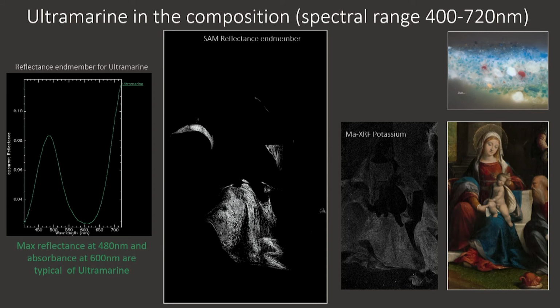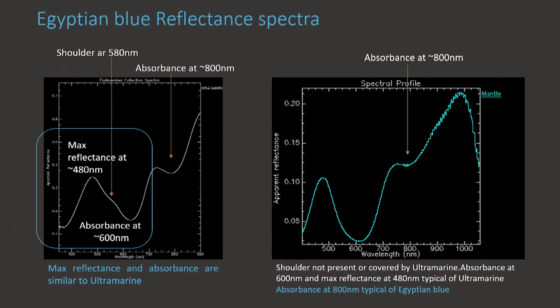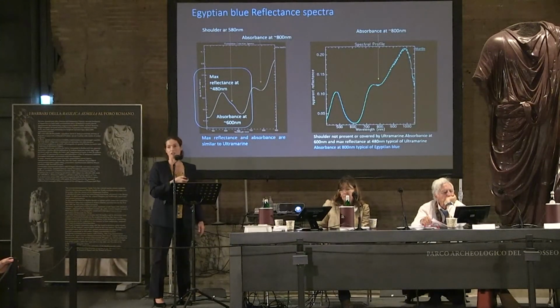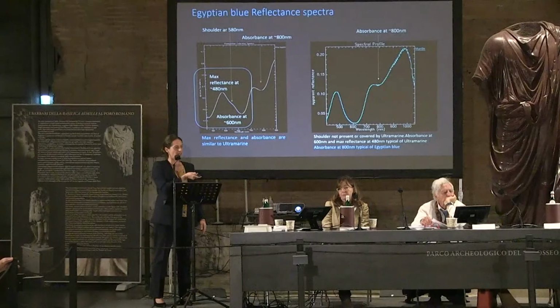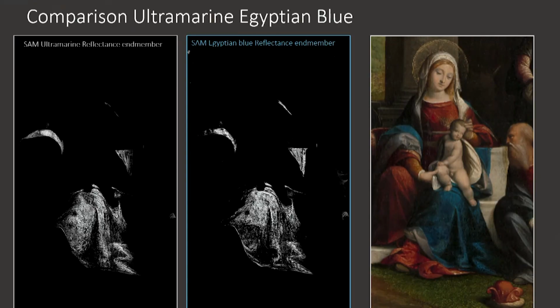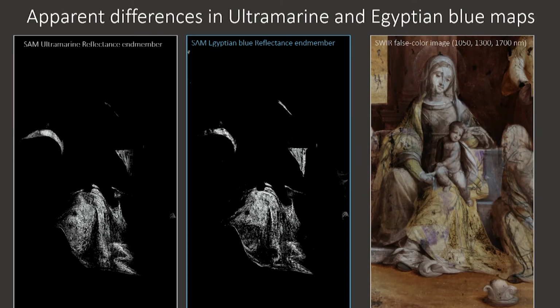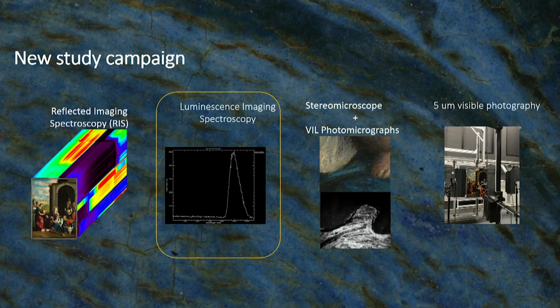But we tried also to map some spectral features typical of ultramarine and Egyptian blue. For Egyptian blue, we looked at the reference spectra and could single out this absorbance at 800 nanometers. And we can compare the 2 maps thus obtained and see that they map the same dark blue elements in the composition, but they don't match completely, meaning that we are indeed imaging different elements. And the 2 differences can be easily interpreted with presence of little damages or over retouches.